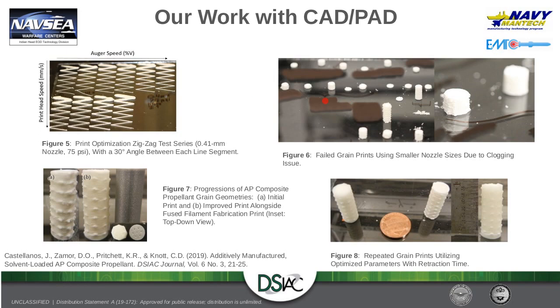These full grains, we chose not to incorporate perforations at first, due to us not fully knowing if we would be able to actually print it with the resolution afforded to us, and us not quite fully understanding how to print the material. But we started first by using the finer of the nozzles that we had available to us. Unfortunately, we were able to produce some grains that were close to full height and did show promise, but that was very few and far in between, simply because the finer nozzles had many clogging events. This caused us to go back to the drawing board in terms of how we would prepare the material to be ready to print.